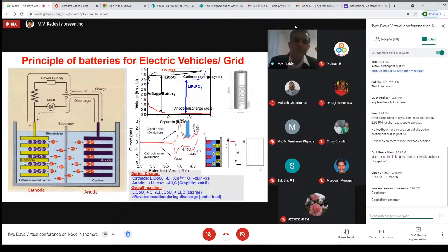So, for example, during charge, if you take a metal oxide and look at the simple voltage versus current plot, you can see that when you remove lithium from the structure, a voltage develops. It means that we can get a plateau. This is called oxidation, meaning cobalt 3 plus to 4 plus. Again, during discharge or the reverse scan, we get cobalt back. This is called reversible, meaning again 3 plus to 4 plus to 3 plus. That's why we call it the redox potential.